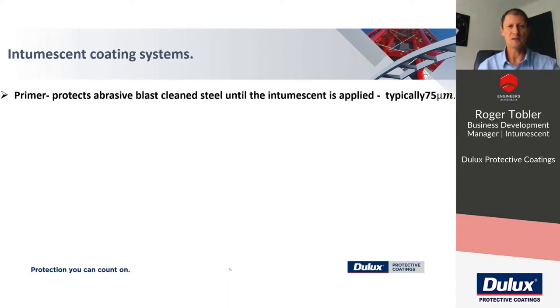So talking about intumescent systems, the first coating to be applied is the primer. It's applied onto abrasive blast-cleaned steel. Typically 75 microns of primer is more than sufficient, provided you've got the correct intumescent system. You're not trying to provide a corrosion protection system by increasing the primer thickness. This is really the coating that's going to keep the steel dry, clean, and in a suitable condition to receive the intumescent.